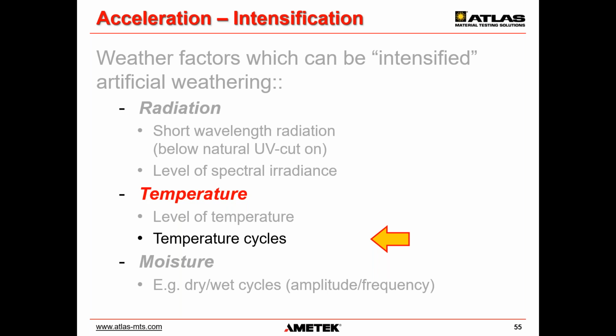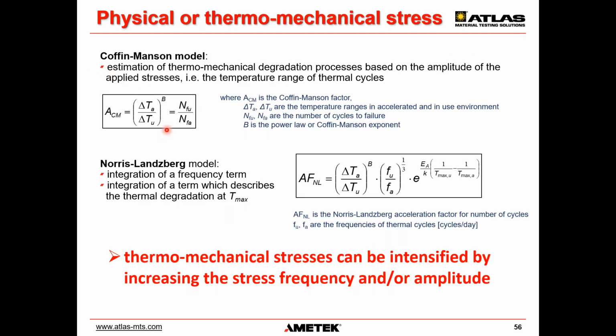For temperature, we can raise the temperature to higher levels, but we also can employ cycling. According to the Coffin-Manson model, the thermomechanical degradation processes are based on the amplitude of the applied stresses, which here means the temperature range of thermocycling, delta T_A and delta T_U. A is accelerated, U is in use environment. And these are the number of cycles to failure. The Norris-Landzberg model estimates an acceleration factor, AF Norris-Landzberg, by multiplying the Coffin-Manson amplitude with a frequency term and the Arrhenius temperature term with temperature max in both environments,